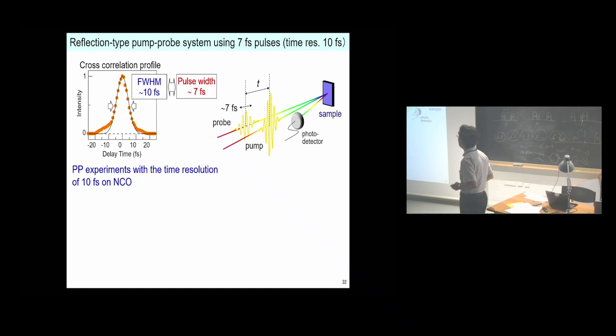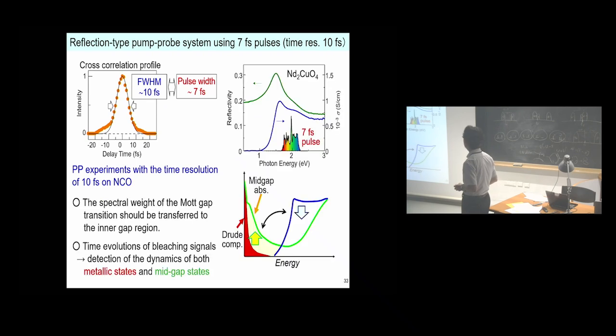To detect them, the time resolution of 10 femtoseconds is necessary. Considering this point, we constructed the reflection type pump probe system using 7 femtosecond pulses and performed the experiment with a time resolution of 10 femtoseconds. A 7 femtosecond pulse has a broad spectrum which is located inside the Mott gap transition. By a photo excitation, the spectral weight of the Mott gap transition should be transferred to the inner gap region. So, by measuring the time evolutions of the reflectivity signals at the Mott gap transition, we will be able to detect the dynamics of both metallic state and mid-gap state.